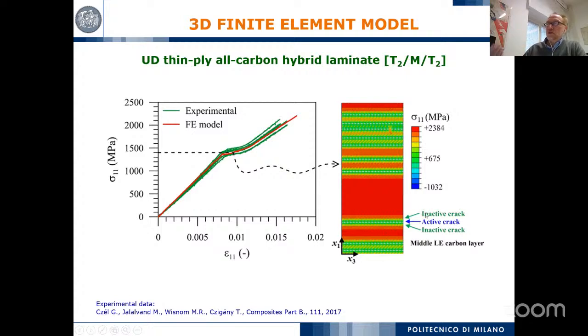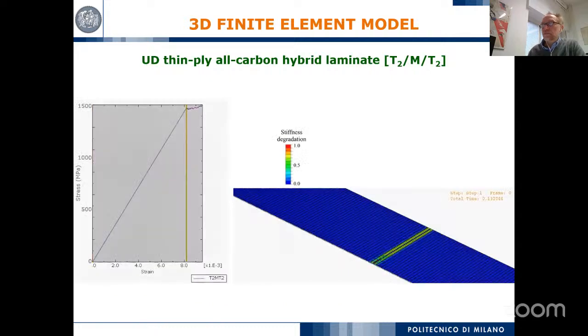So you see the activation of the fragmentation at different positions, and then the activation of the delamination at the place where the fragmentation happened. This is quite interesting because this is the reason why we have this plateau, or rather we can reproduce with the numerical model the plateau that has been observed in the experiment. We can also predict the evolution of the damage; this has been done by looking at this movie.